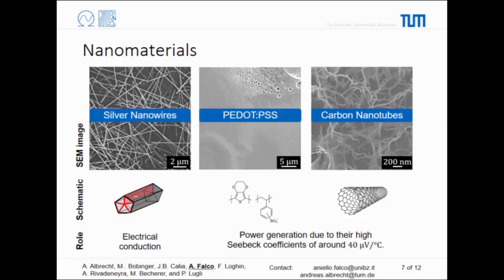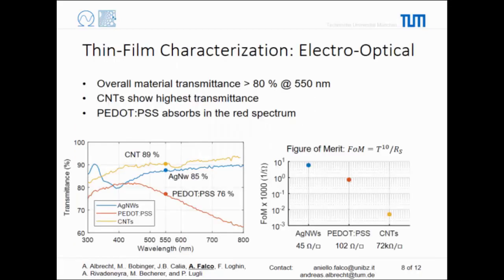So what we do, we put in a solution, we spray deposit it on glass or on PET or on any plastic foil, and then we can see that they are semi-transparent. We analyze the spectrum, so what you can see there on the right side is the spectrum of carbon nanotubes, of silver nanowires, and PEDOT:PSS. Normally, as a reference in literature, you use the transmittance at 550 nanometers, and you just give a number for that.